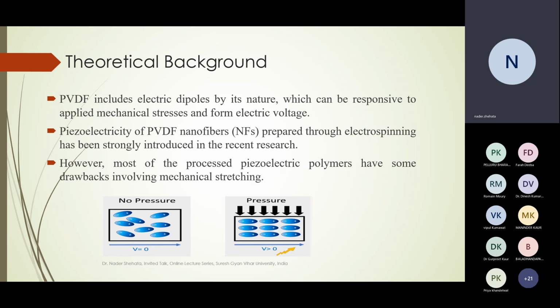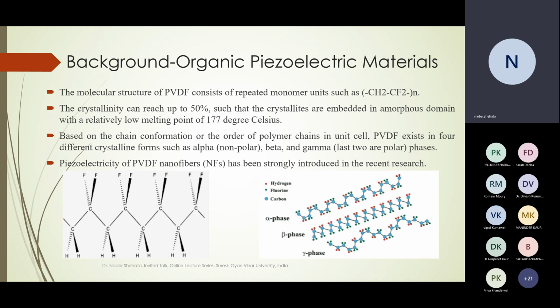However, the traditional techniques of generating piezoelectric nanofibers or polymers from PVDF can sometimes have some drawbacks of lack of mechanical stretching. The stress strain curve is very short. The breaking strain in some cases could be less than 5% elongation. So these are some drawbacks that we will see later how to overcome. Moving in a deeper way to what's found inside the PVDF organic piezoelectric material.